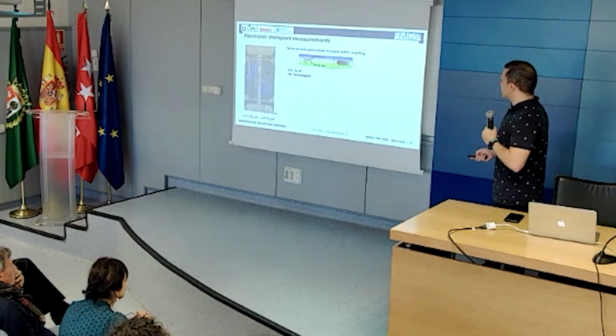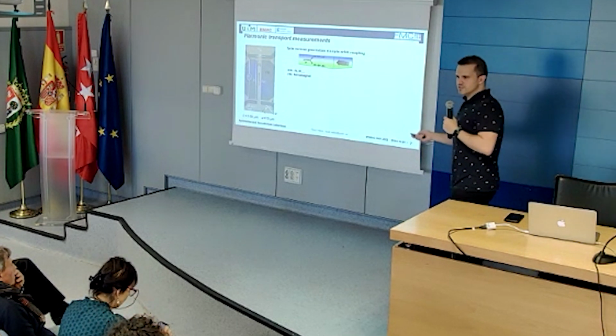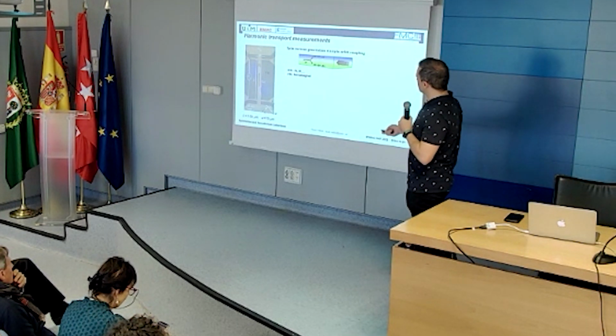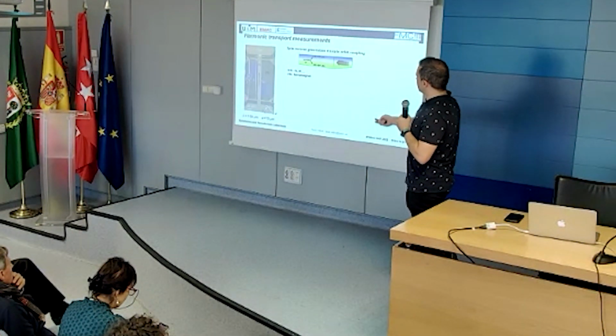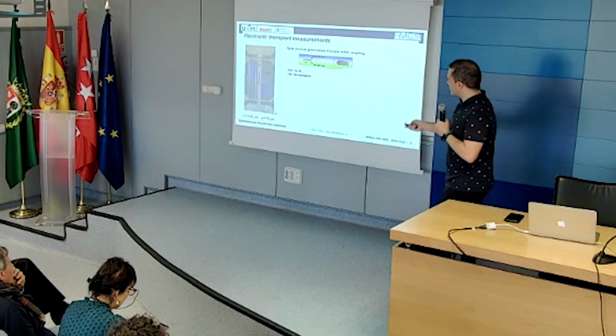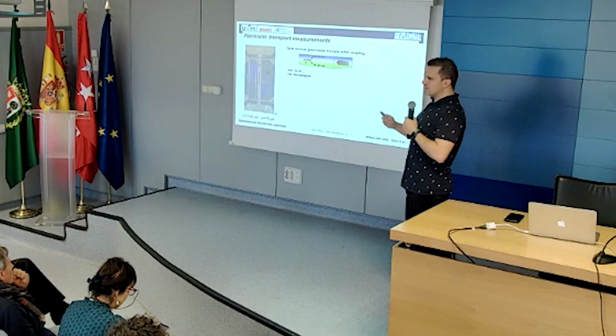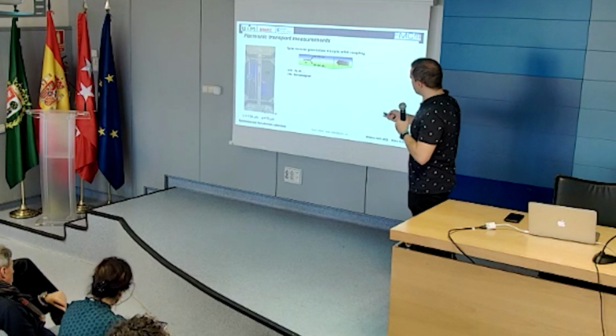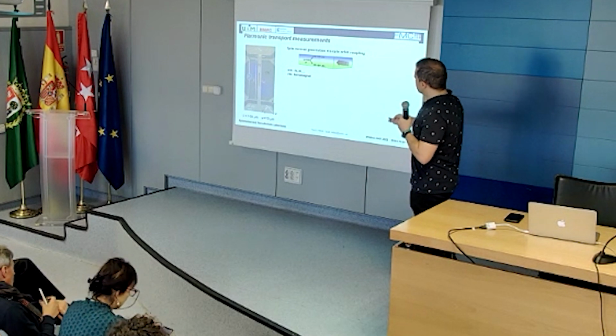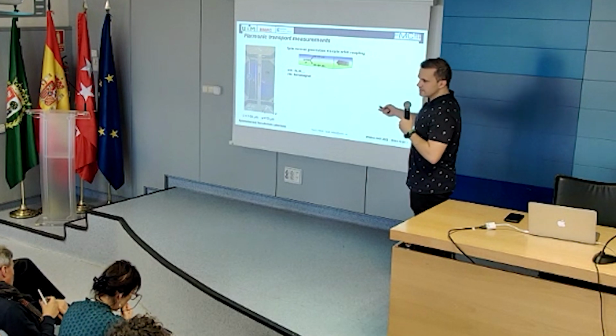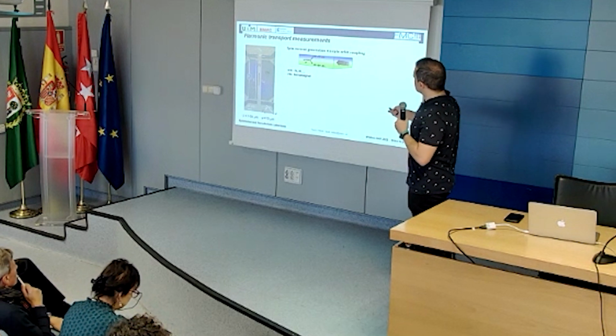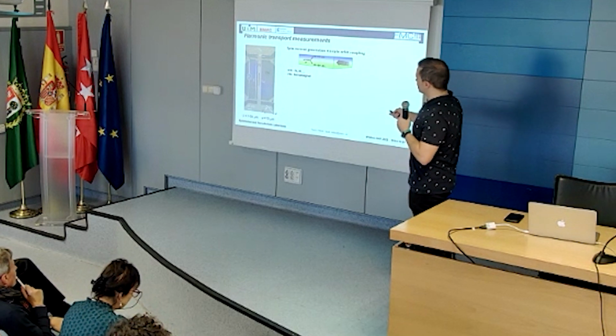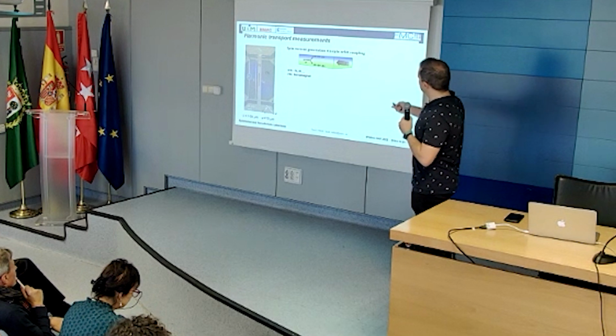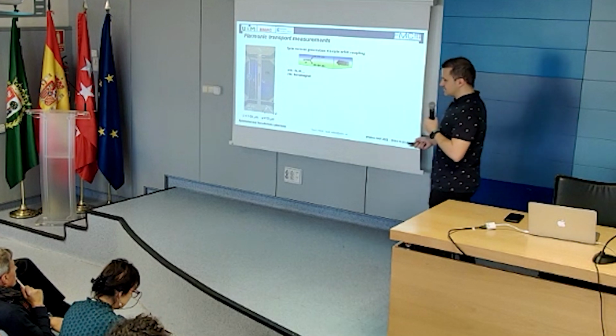What does a measurement look like? What are we actually doing? That's our Hall bar, for instance. Here we run an AC current, and we try to measure the voltage, transversal or longitudinal. In particular, we typically use a material with large spin-orbit coupling. In these materials, when you run a current, you get a deflection of the electrons that depends on the spin. They scatter to opposite surfaces.